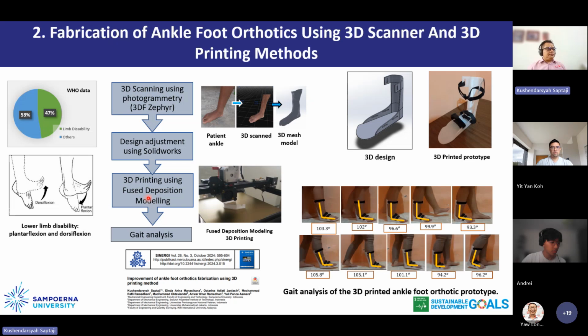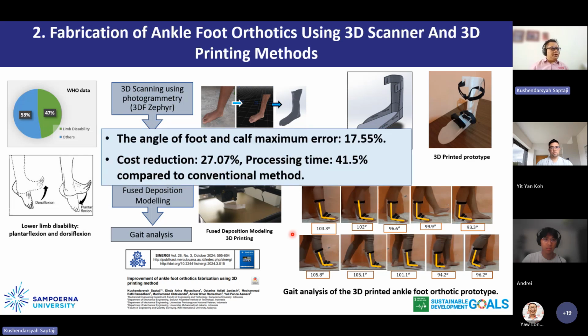And then after that, we print using the FDM process. Once we get the 3D printed prototype, we perform the test using gait analysis. From there, we conclude that the maximum error of the angle of the foot and calf is about 18%, which is good. With this process, we can reduce the cost compared with the conventional method using gypsum normally, and the processing time can also be faster, about 41.5% compared to the conventional method. This work has also been published in a Q4 journal.